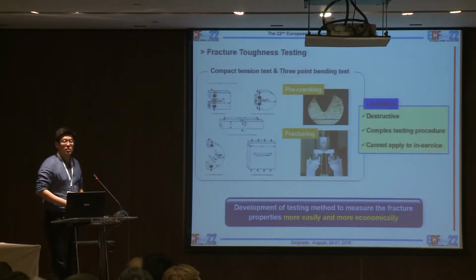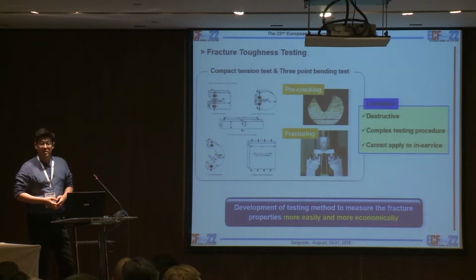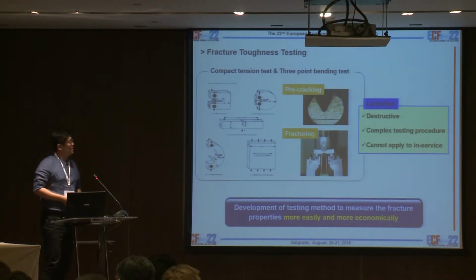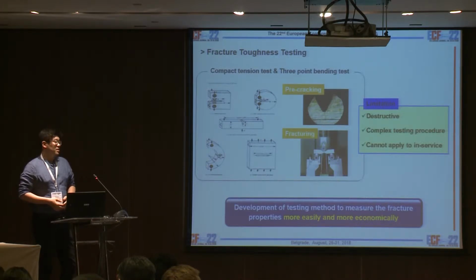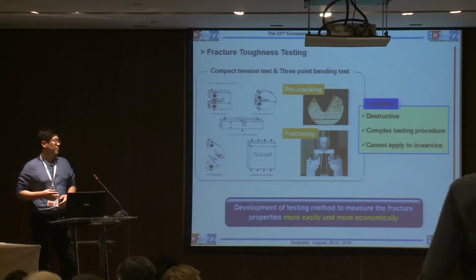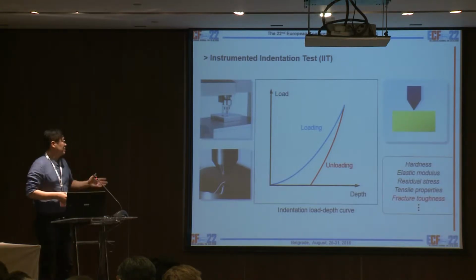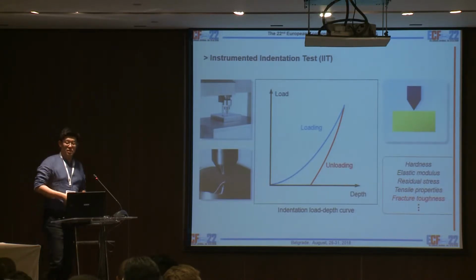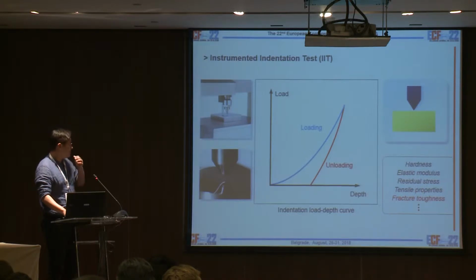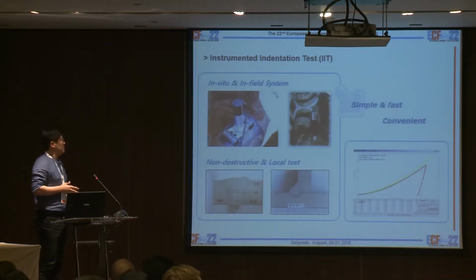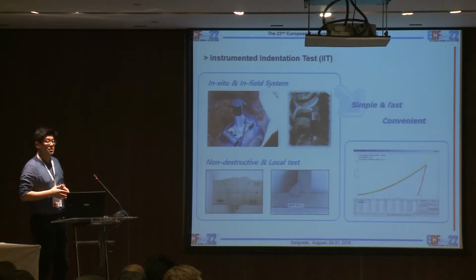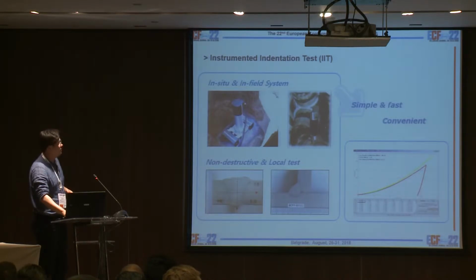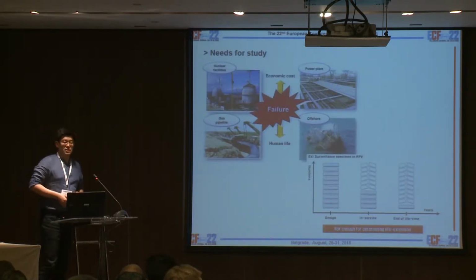As we know, fracture toughness is an important property for structural integrity assessment and product reliability, but the fracture toughness test has a complex testing procedure, and it is a destructive method, so it cannot be applied to in-service structures. But the instrumented indentation test, with simple loading and unloading curves, can give us hardness, elastic modulus, and various mechanical properties. And the most advantageous point is that the machine can be applied to in-service structures with a simple procedure. So this is the motivation of this project.